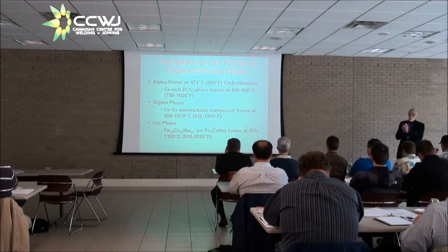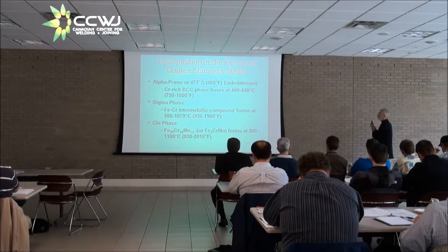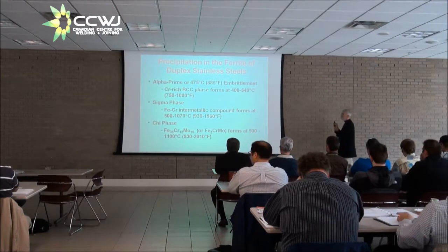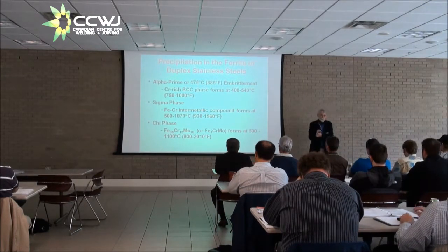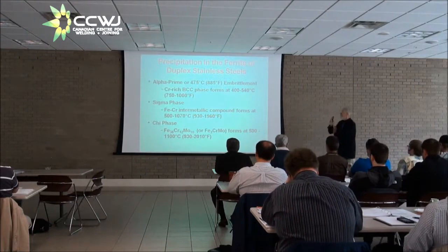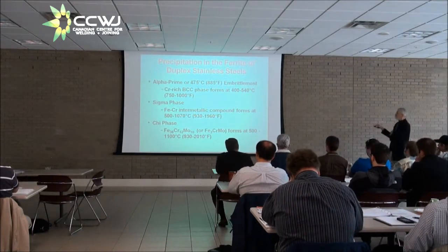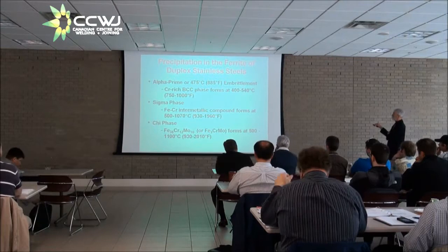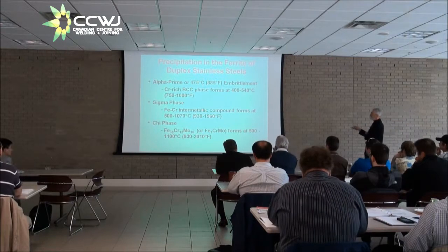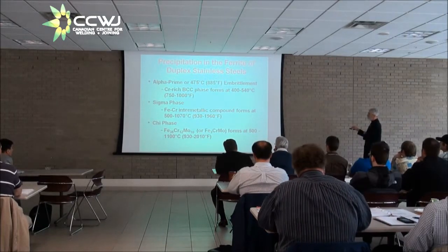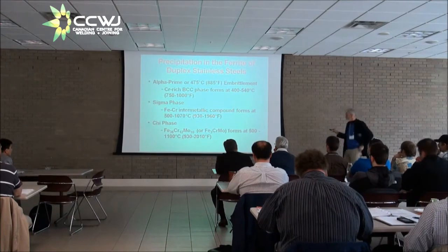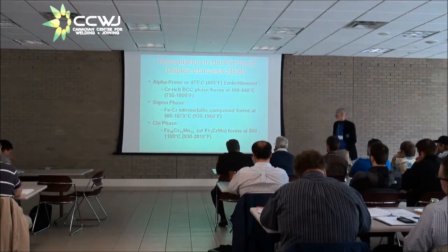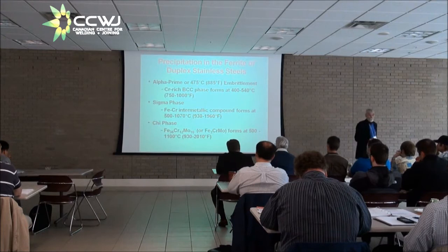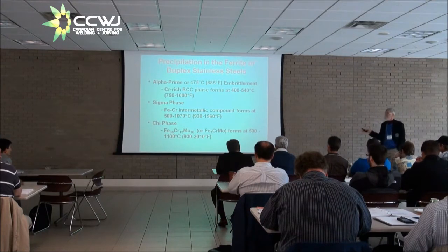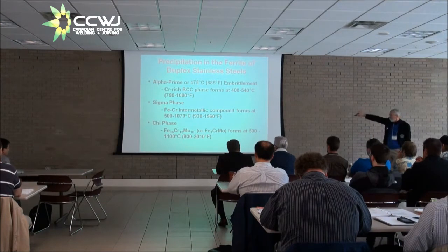Okay, now because of the ferrite phase in the duplexes, there is a lot of possibility for precipitation. These were mentioned also this morning. The alpha prime phase, which forms in a temperature range of about 400 to 540 C. The sigma phase, which forms between 500 and 1070 C. And the chi phase, which can go up to 1100 C. So that essentially prohibits you from using the alloy anywhere from below 400 to 1100.